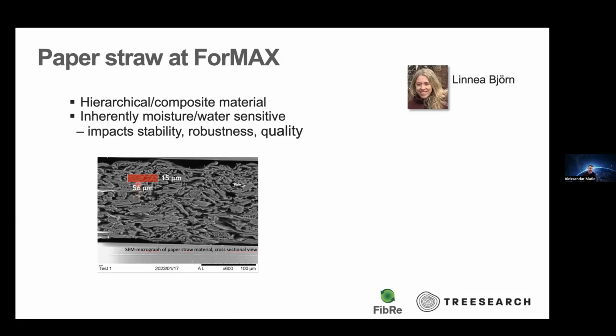So this is a scanning electron microscope image, and when we then later do our SAXS experiment, the beam that we will use is roughly the size of this red square, so some 15 to 56 micrometers. So you can see that here, irrespective of where we focus on the material, we will actually probe, let's say, an average structure of the straw.